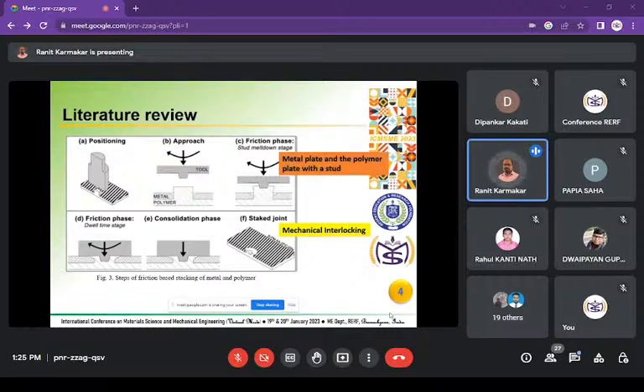Besides that, there is another method to join metal and polymer, which is friction-based stacking. Here the metal plate with the polymer plate with the stud is used. The stud is inserted in the metal plate with a hole, and then the tools are approaching through the stud and the hole, and after the rotating, the frictional heat is going to melt the polymer, and by the mechanical interlocking, the joining happens.